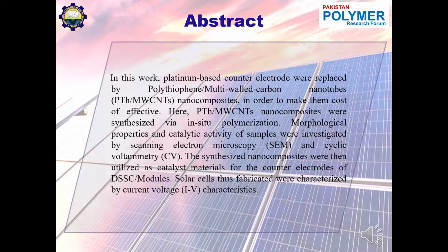In this work, platinum-based counter electrodes were replaced with polythiophene multi-wall carbon nanotubes-based nanocomposite in order to make the cell cost-effective and more efficient. In this work, polythiophene and MWCNT-based nanocomposite was synthesized via in-situ polymerization, whereas after synthesis, the morphological properties and catalytic activity of the sample were investigated with the help of scanning electron microscopy, FTIR, cyclic voltammetry, and many more characterization techniques. The synthesized nanocomposite was then served as a catalyst material for the counter electrode of the dye-sensitized solar cell module, and the solar cell was fabricated, which was investigated via current voltage characterization.